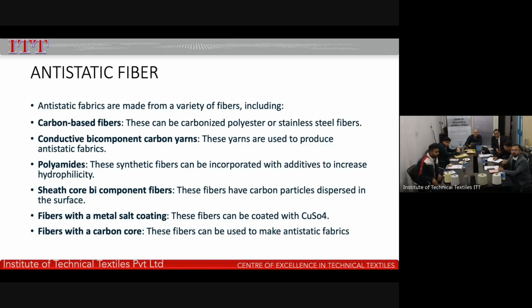Then another fiber which is mixed to give some special property to the FR garments is the antistatic fibers. They can be carbon-based fibers, or they can be conductive bicomponent yarns, or they can be polyamides with increased hydrophilicity. Then sheath core bicomponent fibers, fibers with metal salt coating, fibers with a carbon core.